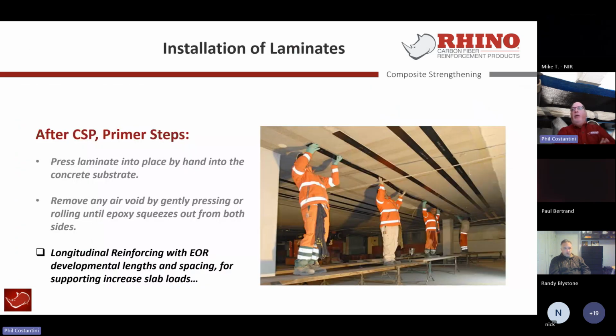So typically, again, jumping back to the laminates, the carbon fiber laminate world really did a nice job in their pre-curing of their application with how these are produced. And when you have long runs, it's really nice to work with the laminates, and they're pressed and applied with the structural adhesive that bonds to it. And then you have to remove the air voids, pressing the rolls up against it and squeezing the epoxy out from both sides, and then flaring it back onto the underside of this application, directly over top of the carbon fiber, so you don't have to waste any material falling on you or onto the side.